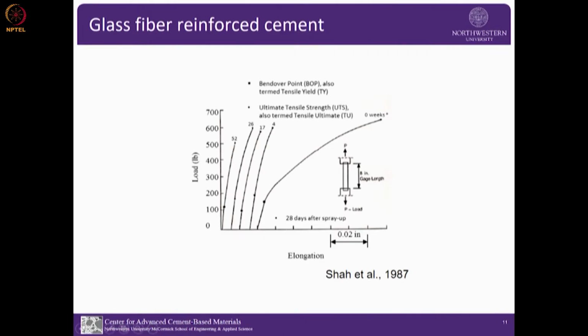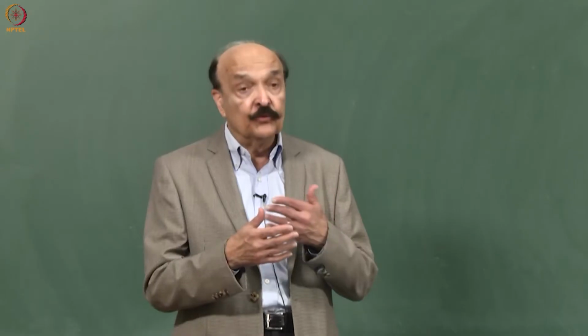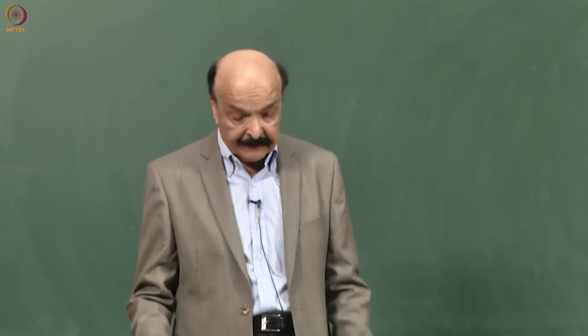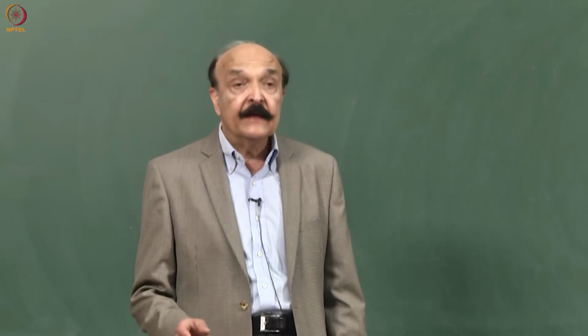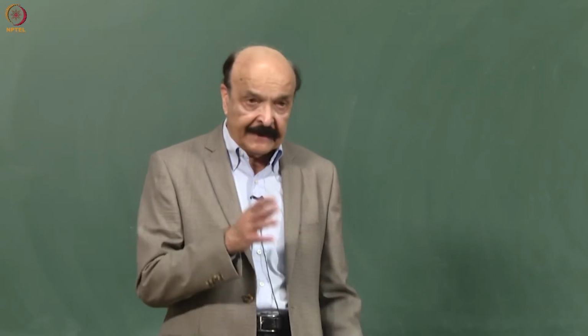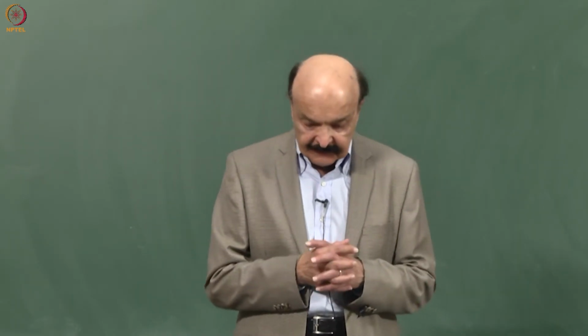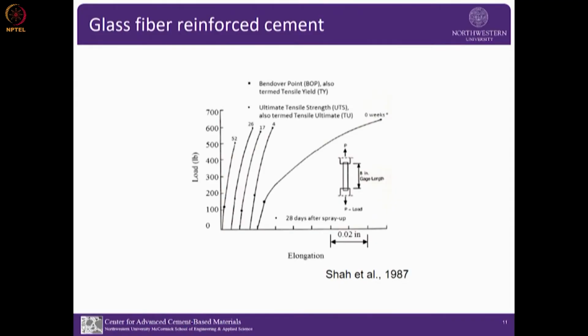So if you look at the 28-day, this is sprayed-up glass fiber reinforced. So you have a linear behavior. People often call this bend over point, and then you have this nice multiple cracking and strain hardening response. And this is 4 to 5% of glass fiber. So with this technique, you can use longer glass fibers and higher volumes. So great response. Then we subject that to this accelerated aging, I think about 60 or 65 degrees in lime water,